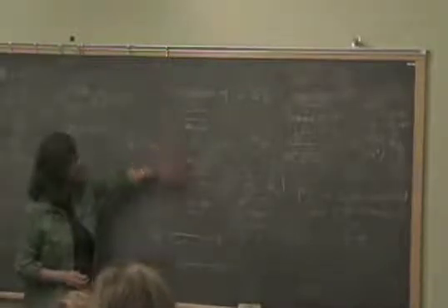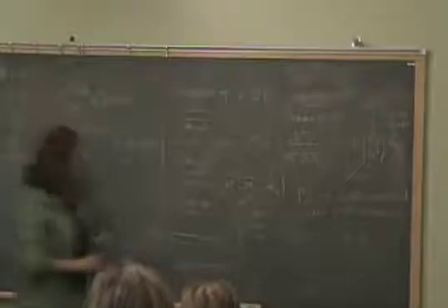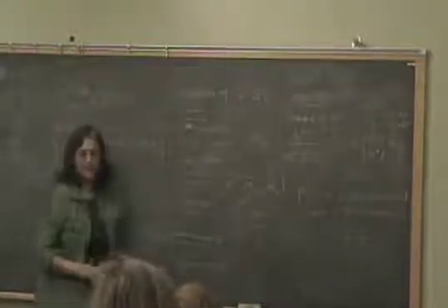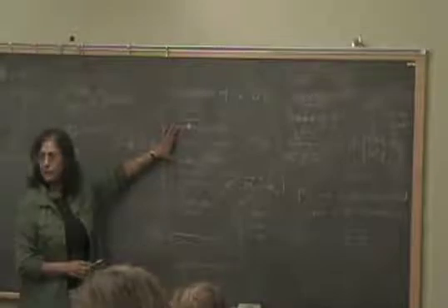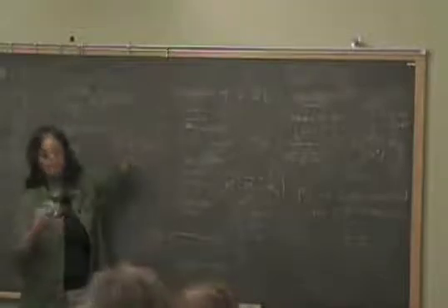Okay, so the main point about an exciton is that you will get absorption in a semiconductor or in a quantum dot, which is below what you would have calculated to be the gap. So in this case, you may have calculated, this is my highest, what is it called? LUMO HOMO, lowest unoccupied, highest occupied molecular orbital. Okay, so you can calculate these things and you'll say, okay, this is my gap. But if you do an absorption study, you will find that you'll get absorption at a slightly lower energy given by this exciton effect.